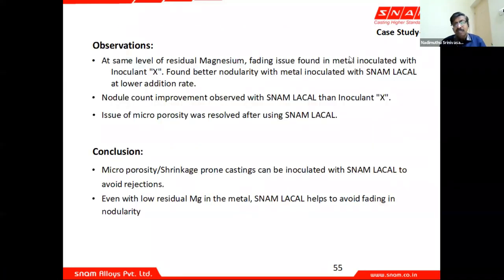So at the same level of residual magnesium, the fading issue is found to be addressed better when we have SNAM-LACAL and a lower addition rate. Nodule count improvement was seen, and the tendency for microporosity has been eliminated. So even with a low residual magnesium, which means not increasing the magnesium.